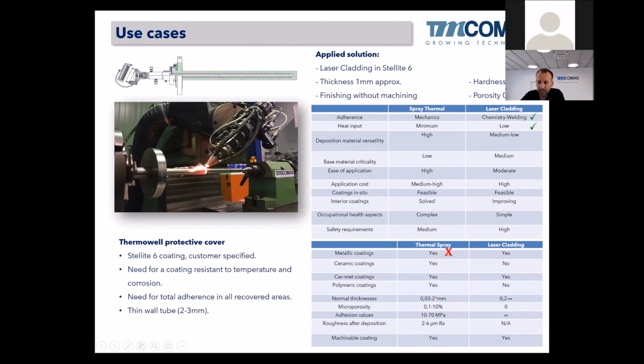So we are using the laser. We are using the laser also with a special device control that controls the laser power. As soon as this camera here detects that the melting pool is increasing because of the heat input, there is a reduction of laser power. So the heat input decreases to keep a constant dimension of the melt pool.